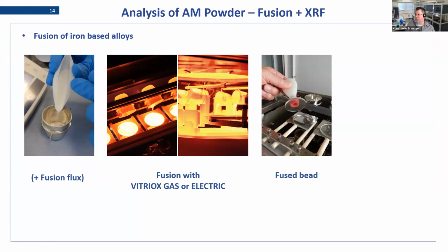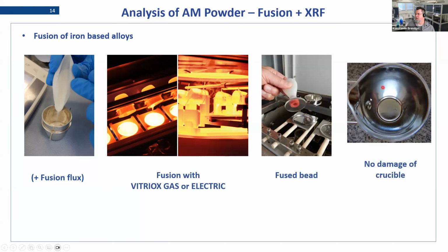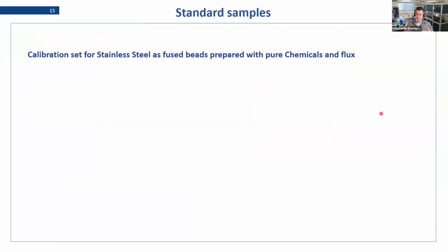The whole idea here is to get a good fused bead, and most importantly, to prevent any damage to the crucible. The problem with metallic powders, you're probably aware of this. There's also, I think, another episode of this series where we talk about it. It's dangerous to work with metallic samples in general on platinum, so you have to stick to these procedures to get your fused beads without damaging the equipment and your platinumware in the end. You want to use it for as many fusions as possible, so you want to be careful.